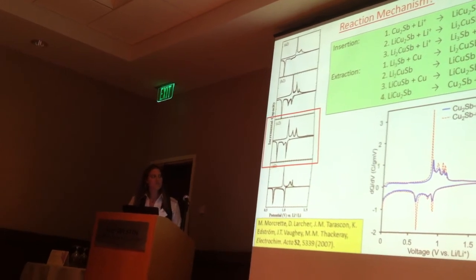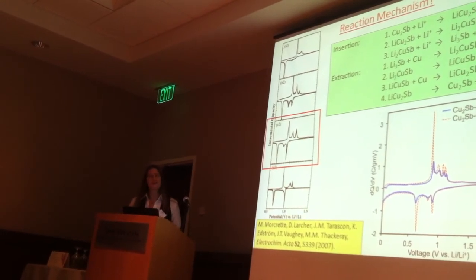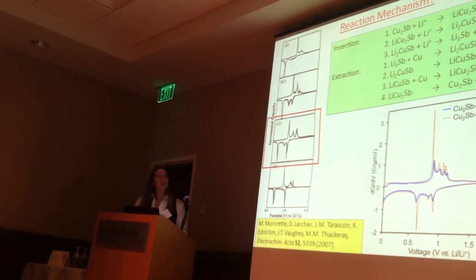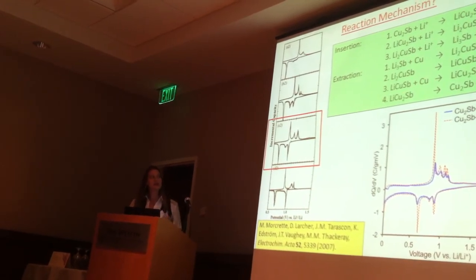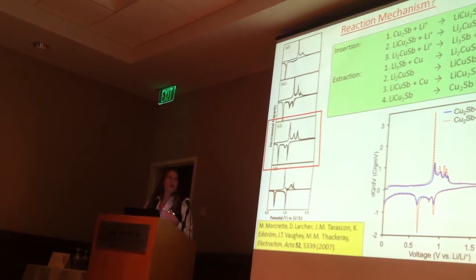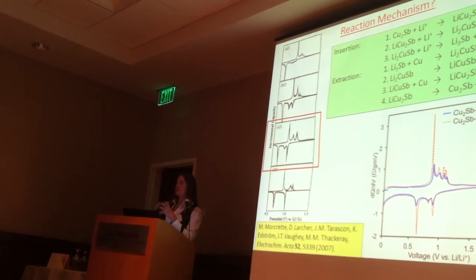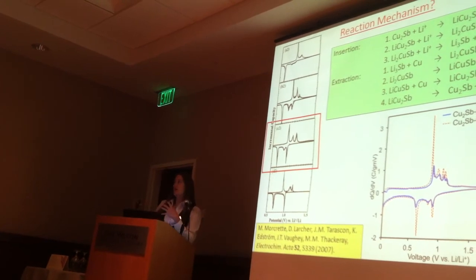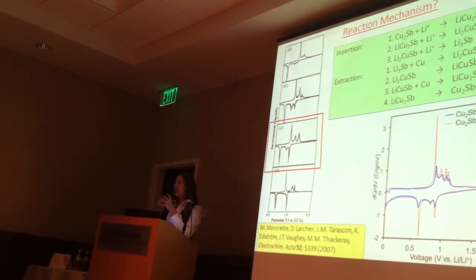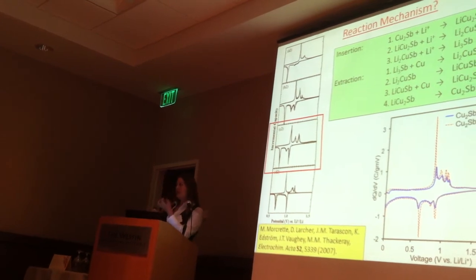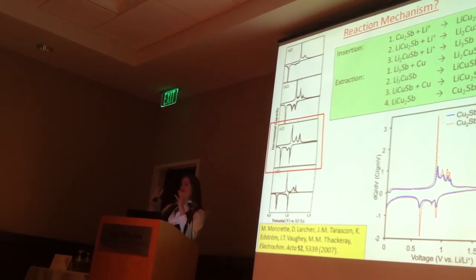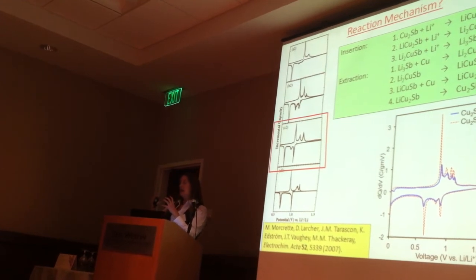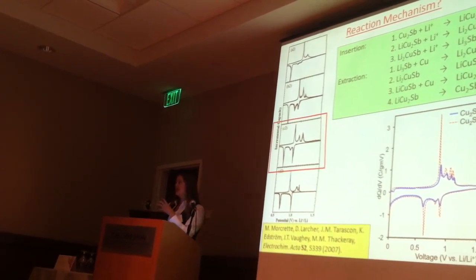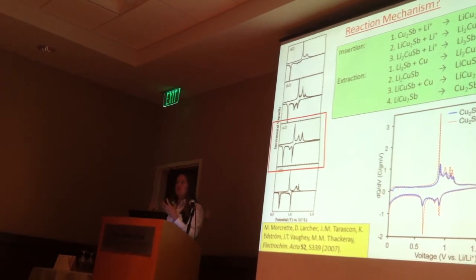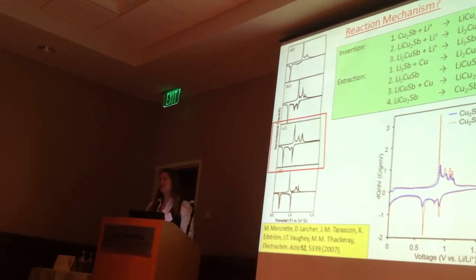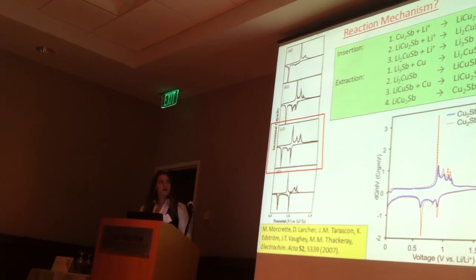And I find that really interesting, and we'd like to figure out what the reaction mechanism is. We have a few ideas about what it might be, and our thinking is that maybe when you constrain these particles to a small size, when you extrude the copper and you insert the lithium, and then you have to undo that reaction, you have a very small particle that's surrounded by aluminum oxide and carbon, and that copper is not limited by its large size. It can go into and out of these small particles more reversibly than if the particles were larger. So that's kind of where we're at with this material.